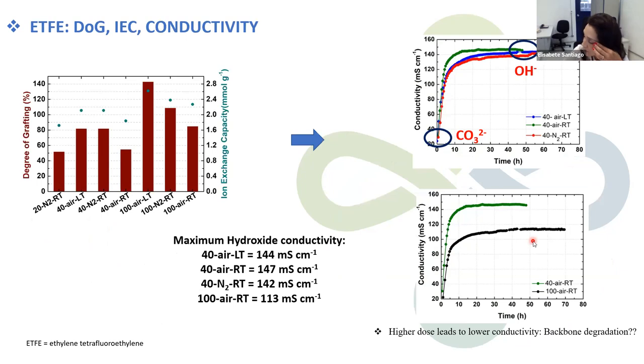So here I show you some results of degree of grafting and the ion exchange capacity, as a function of the atmosphere, radiation dose rate, and temperature. Here the membrane is produced at 20, 40, and 100 radiation doses, under nitrogen and air, and at low temperature and room temperature. I mean, low temperature is 0 degrees and room temperature is something like 25 degrees, okay? So here the conductivity is also influenced by the radiation, the radiation atmosphere, and the temperature.